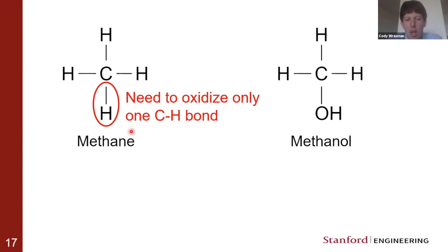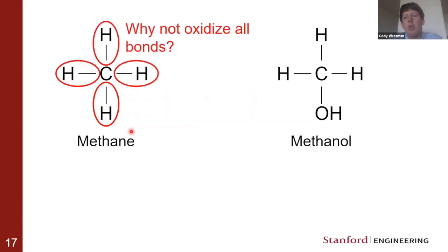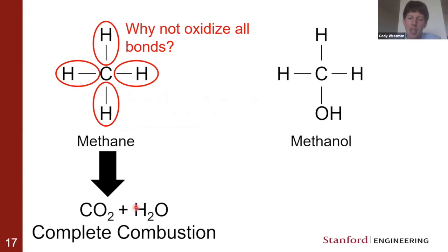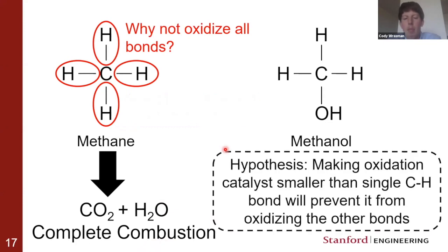But the challenge really becomes, if you have conditions that you can oxidize one of those bonds, why wouldn't you just oxidize all of them? And that's actually what happens with all catalysts thus far. You oxidize all of those bonds, and you make carbon dioxide, which is not really a valuable product at all. So our hypothesis on this project was, maybe if we make the catalyst so small that it's only large enough to access one of these CH bonds at a time, we might be able to avoid oxidizing all of the other bonds.